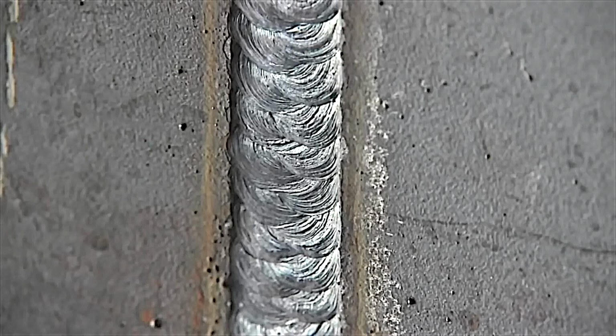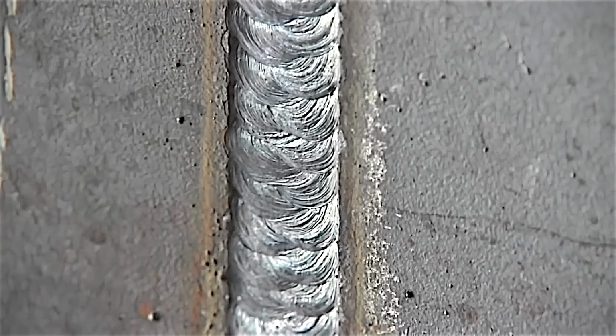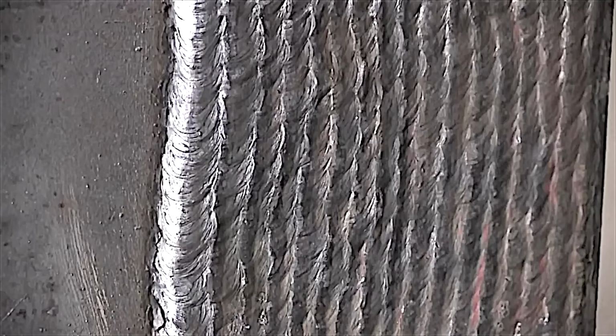Now, there's also times when you want to use a smaller rod. A 3/32 7018 is a super useful rod. 90 amps is a good hot setting for that. And here's a vertical weave. This is done a lot on Schedule 40 and Schedule 80 pipe, but also on heavy equipment repair, on gouged out cracks and things like that. And this is just a 1/8 7018 uphill practice pad bead with 125 amps, which is something I highly recommend if you're having any trouble at all welding vertical uphill. Pad beads, get some seat time, get some hood time, get plenty of practice.